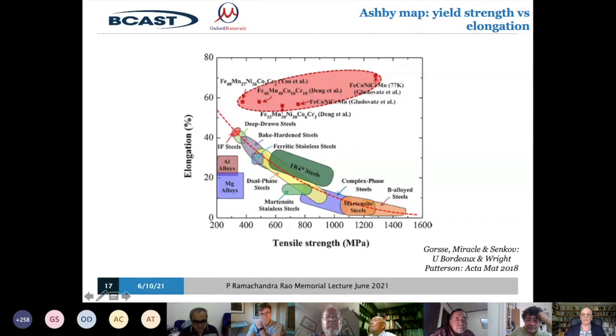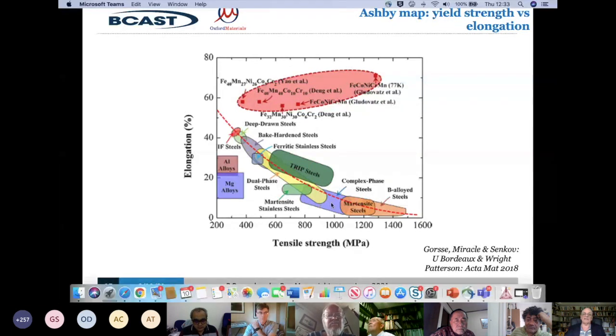And another point to notice, though, is that there's an awful lot of them. As I said already, there's a massive sea in the middle of that multi-component phase space. There is a massive region full of millions and millions and millions of different Cantor alloys, face-centered cubic alloys with different compositions. We've only just begun to look at a few of them, to be perfectly honest, and you can see they have a range of properties, but in broad terms, you can get from the Cantor alloys already strengths in the 0.5 to 1.5 gigapascals along here, and ductilities and fracture elongations in the range 50 to 100%. Which are really outstanding ranges. And we haven't really optimized them yet.